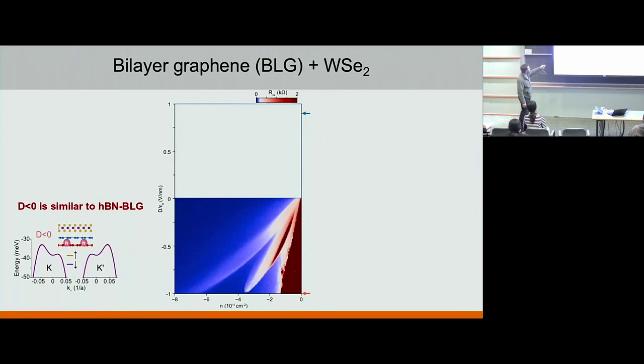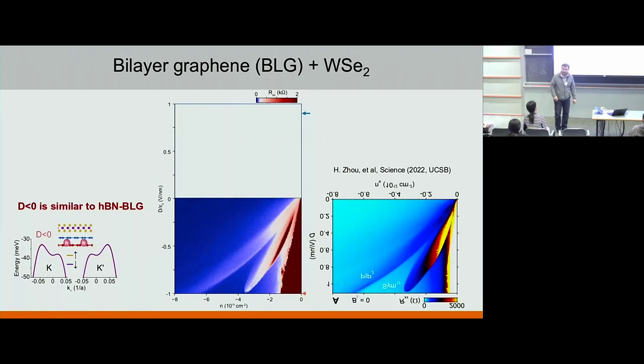in part for the reason that if you do the experiment with the bilayer graphene, apply this large displacement field, and investigate this range of dopings and displacement fields, you see a phase diagram encoded in this resistance. If you compare this portion with previous work done in Andrea's lab, where he did not use tungsten selenide, up to the inversion symmetry that had to be matched, everything else is matching. The doping range is exactly the same, the displacement field is exactly the same, and even the color map boundaries in resistivity are exactly the same. So that means that if there is a Rashba, it's somewhere there, but it's hiding in this case.